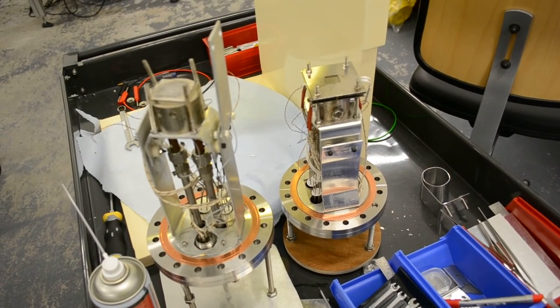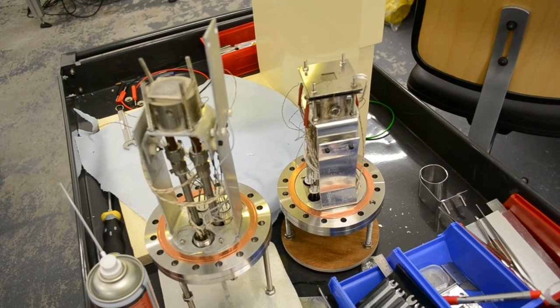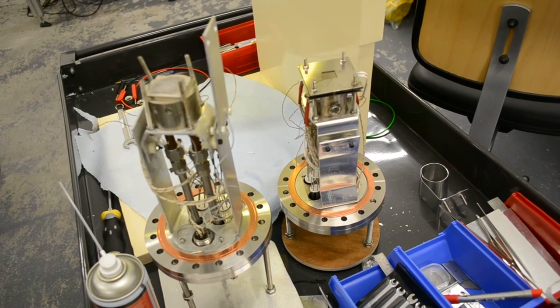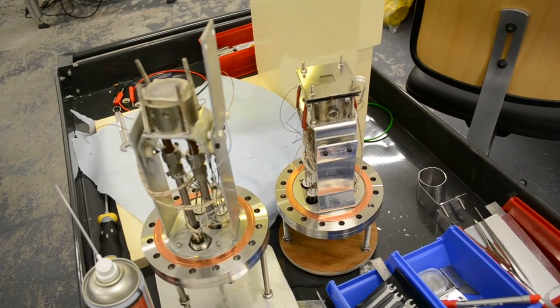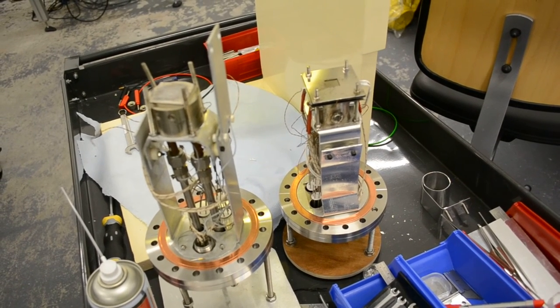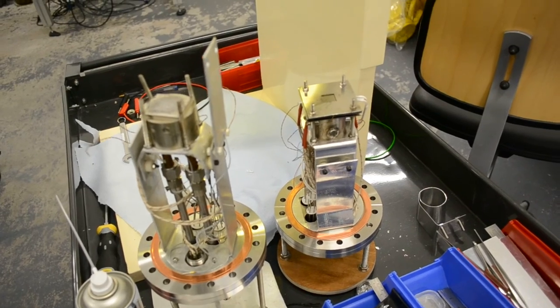The stage can heat the sample up to 400 degrees and temperature can be monitored simultaneously by thermocouples and thermographic camera. Also, there is an electrometer to measure accurately the charge deposited on the sample.